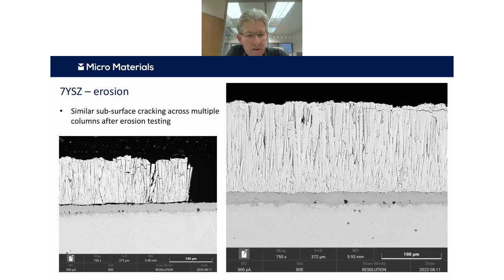And what's interesting is if you look at erosion scars, essentially, then you can see similar sort of cracking across columns, as you can see on the right. And also if you're quite near the center of the scar, you can get some more extreme cracking and also loss of the structure, as seen on the left. So very similar crack patterns that you see in both types of test.